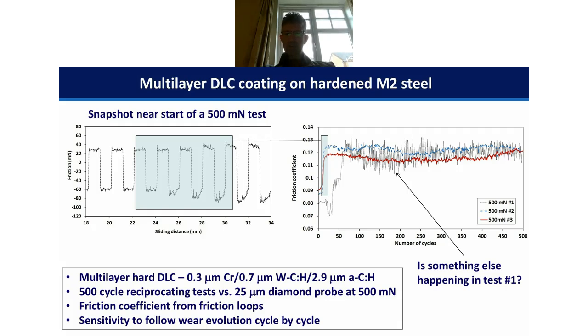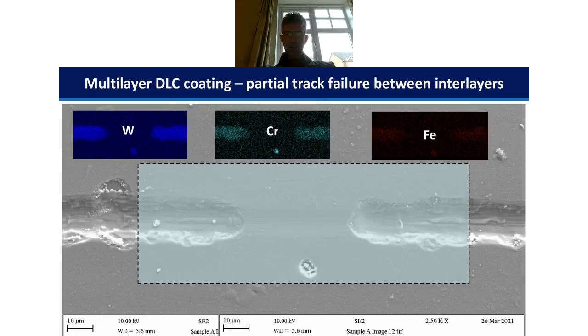friction versus cycles. So we've done some SEM in collaboration with Manchester Metropolitan University. And what we can see here is that there's partial failure over that track. Some regions are intact. Some regions you have this fracturing. And then you get this exposure of the tungsten coming from the sublayer. So essentially you're getting a cohesive failure mechanism within that coating system. And that's quite important in terms of coating design. And it's a bit of a limitation.